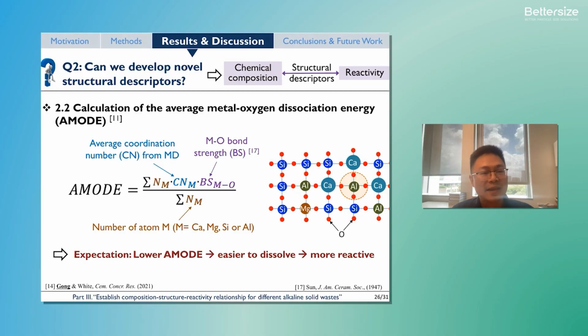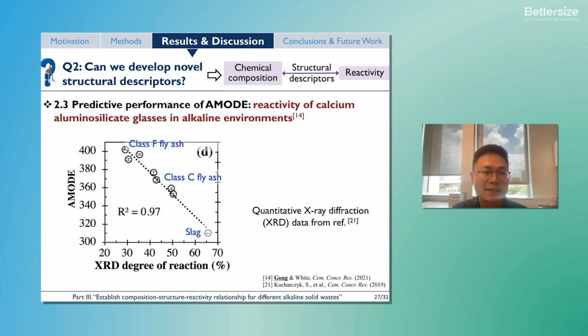Now let's look at the performance of these Amode parameters in predicting the relative reactivity of calcium aluminum silicate glasses in alkaline environments. These calcium aluminum silicate glasses are designed to simulate different slag and fly ash. Fly ash is an industrial byproduct from coal-fired power plants. Now, we can clearly see an inverse correlation between these Amode parameters that we get from the atomistic simulation and the extent of reaction from quantitative X-ray diffraction.